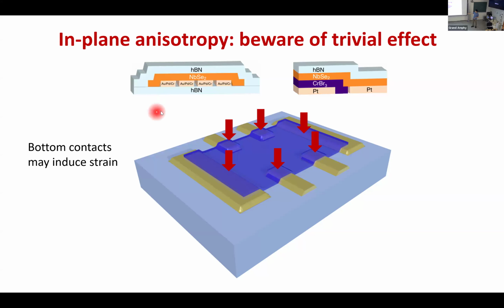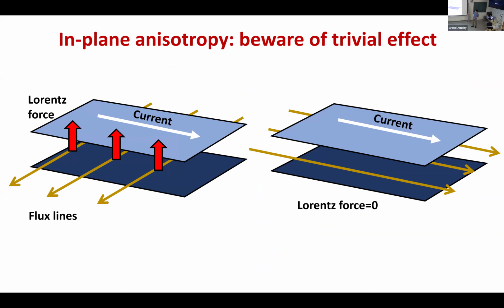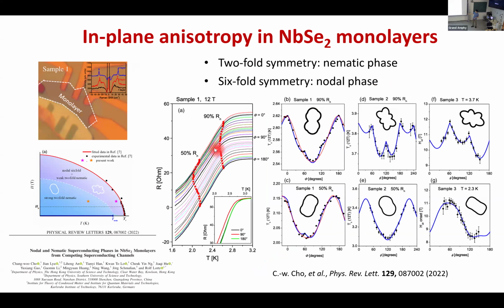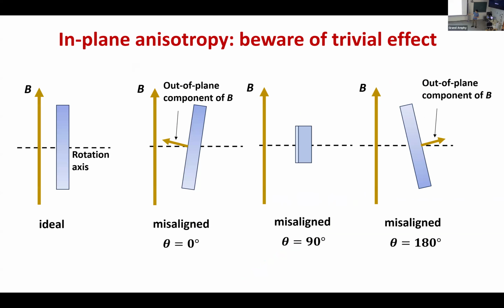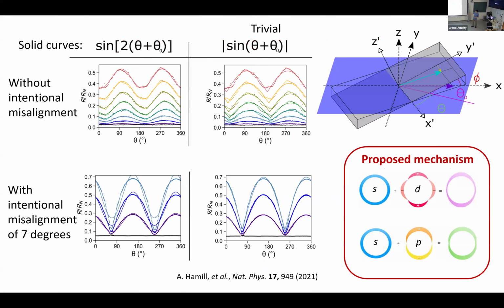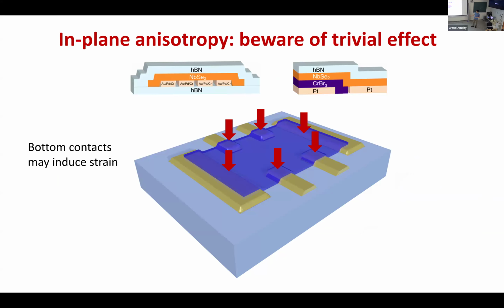So look at this picture, when they observe the six-fold symmetry, you see that there are so many contacts, and these contacts really can disturb the flatness. And some people tell me that different alignment of the contacts can also disturb flatness if they come from the top, not only from the bottom. They strain, and sometimes you're actually folding up the material. Once your reference is a single atom, it's really hard to stay flat on a single atom. So this is something we all need to be aware of.